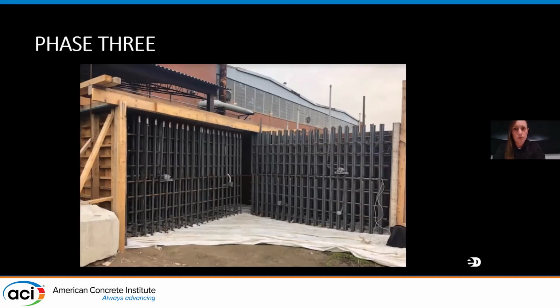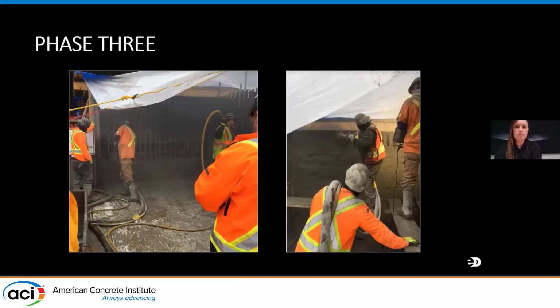This is also used to pre-qualify the nozzlemen and contractors to work on the project, which we found is very, very important to do. 2 contractors were invited to shoot identical mock-ups with the equipment and procedures of their choosing, but they did use identical pumps. There were noticeable differences between contractors though. One shot at 2 times the pressure of the other. One used a stiffer rubber tipped nozzle to promote the consolidation of the concrete in the back of the wall.